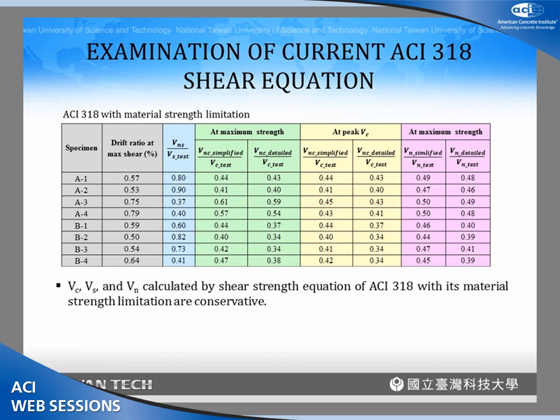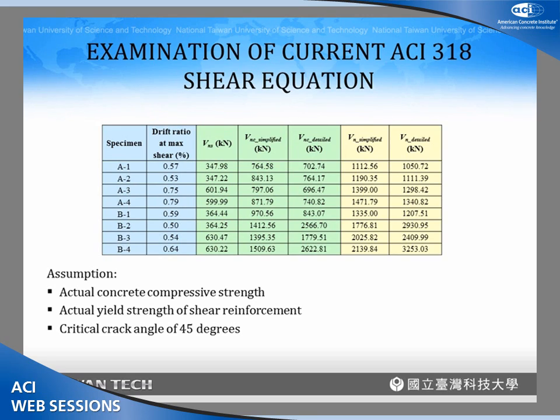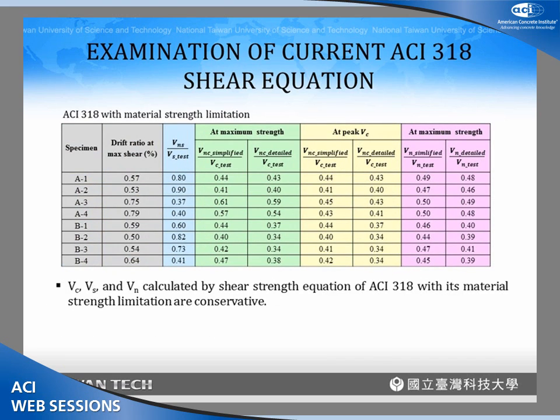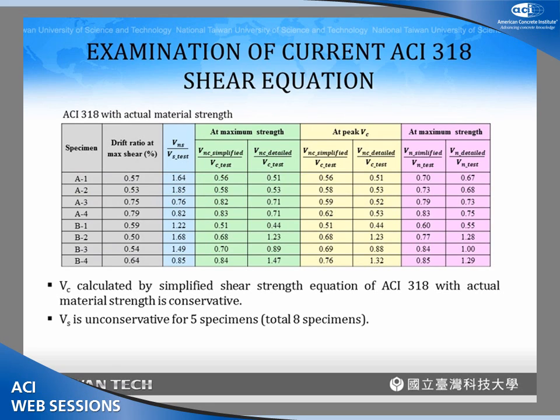So if you use the ACI shear strength equation with all the material limitation in the code, we found that we are able to get a conservative result for Vs evaluation, for Vc evaluation, simplified and detailed, and also, of course, for the Vn calculation. So the ACI code with the material limitation is conservative for high-strength concrete columns. And then we try to challenge the material limitation. We increase the concrete compressive strength to the actual measured in the testing, and we increase also the yield strength of the shear reinforcement to the actual yield strength.